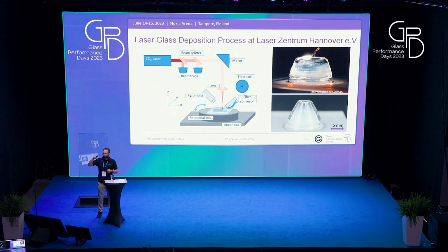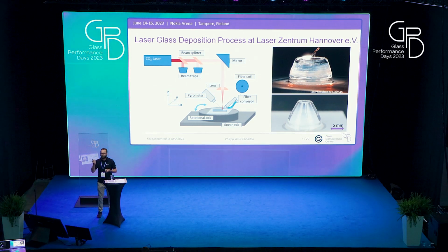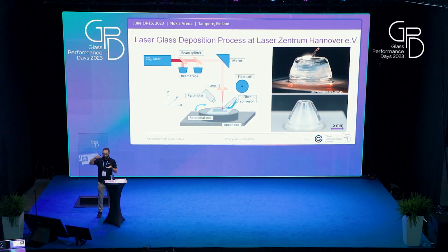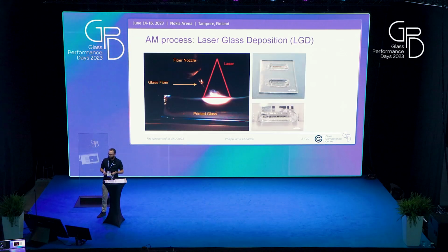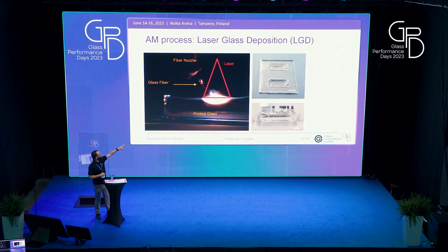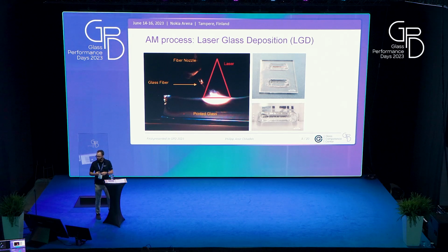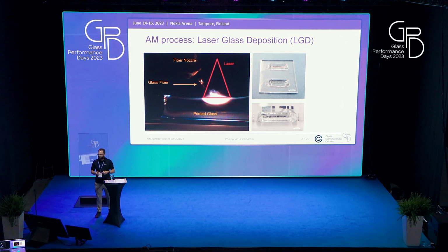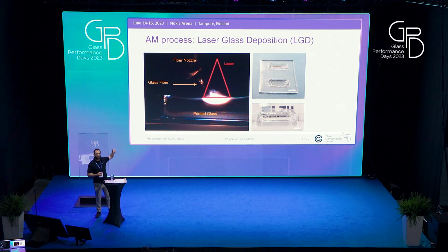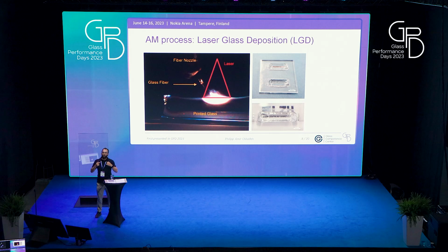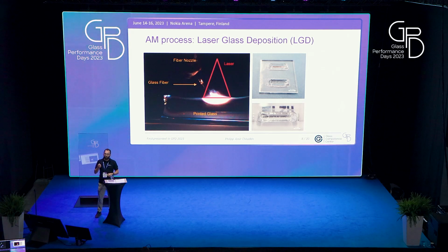They have quartz glass fiber, which is 0.4 millimeters thick, so very thin fiber. They feed it to the point where the laser is, and then they melt it there, which is also a bit better shown in the next slide. We can also see the specimen we looked at for this investigation. So the conveyor feeds the glass into the laser beam,